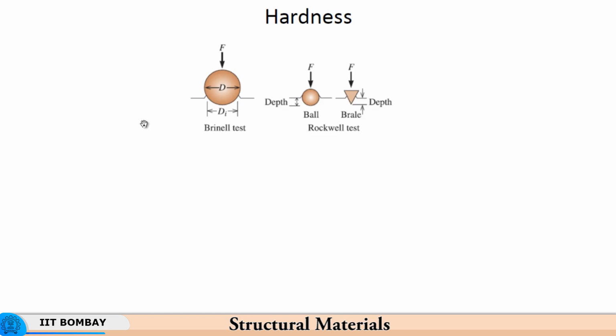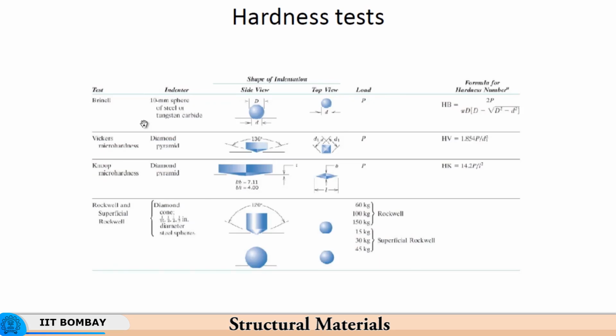So, the Rockwell test does not give you the stress, whereas a Brinell test gives you a stress. So, you can correlate the stress determined by the Brinell test and the yield strength of the material if there is no surface hardening treatment being given. So, if the surface hardness of the material is representative of the bulk properties, then you can even measure the hardness of the material at the surface and correlate that with the yield strength of the material. I mean, you can't take that as the yield strength, you can correlate that with the yield strength of the material. So, we will see that in a minute.